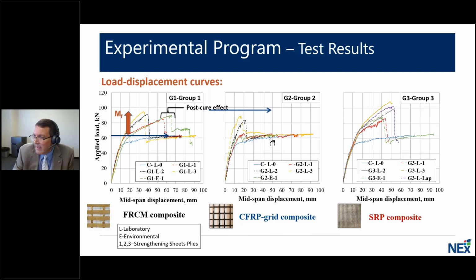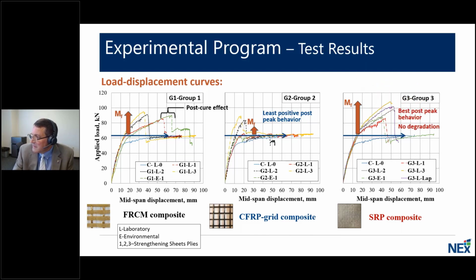If we look at group 2 now, we see that the CFRP fiber, which has actually much greater tensile capacity, did not necessarily result in improved capacity, or for that matter, it didn't result in the best post-peak behavior. And then finally, for the one-way slabs with SRP, in terms of the epoxy curing agent, it did provide better capacity, although the tensile capacity of the steel is higher. But then it also provided a little bit better post-peak behavior. And in none of these systems did we see significant degradation,